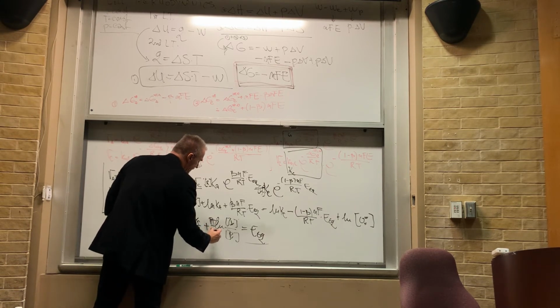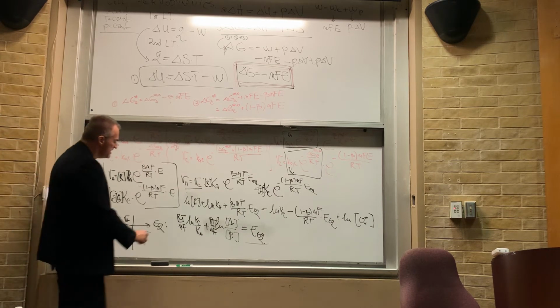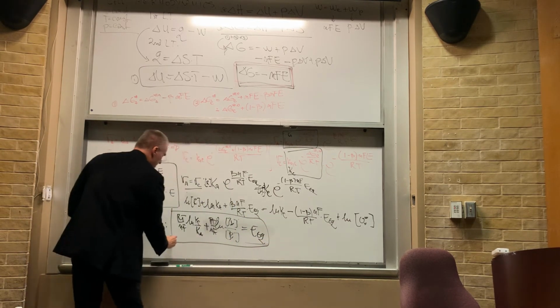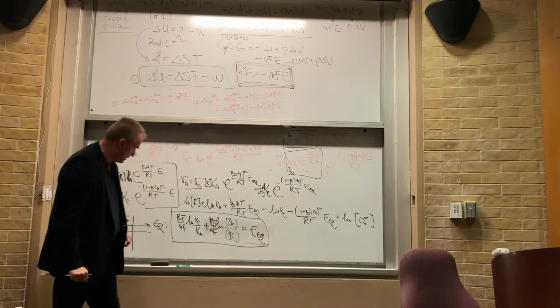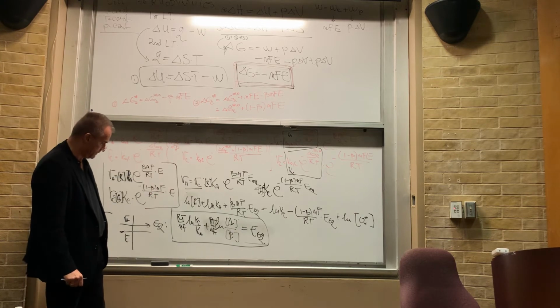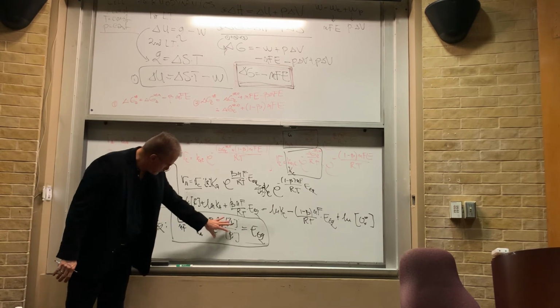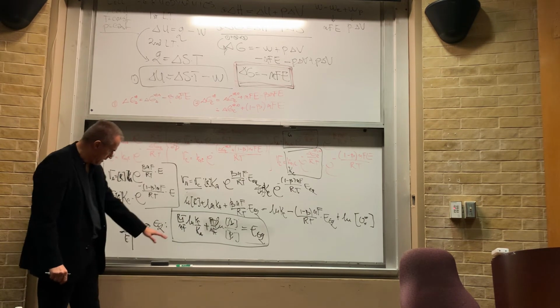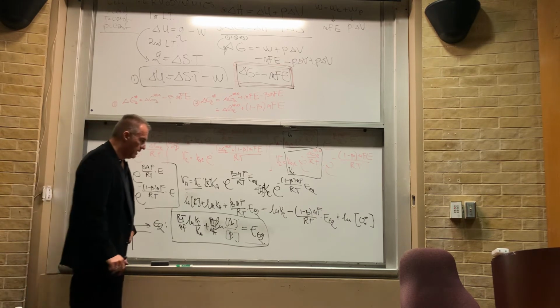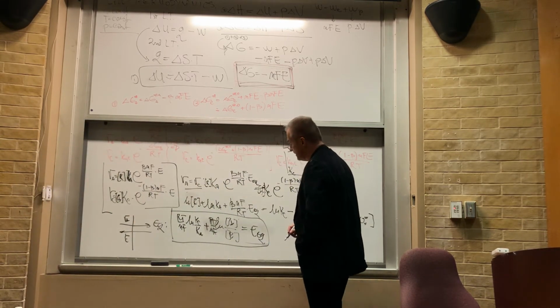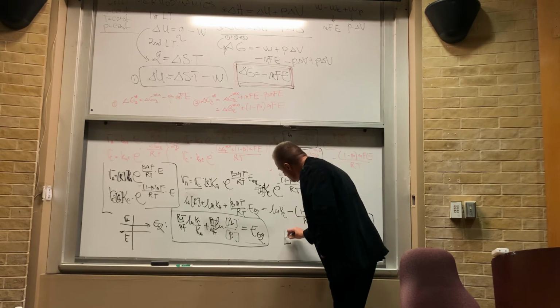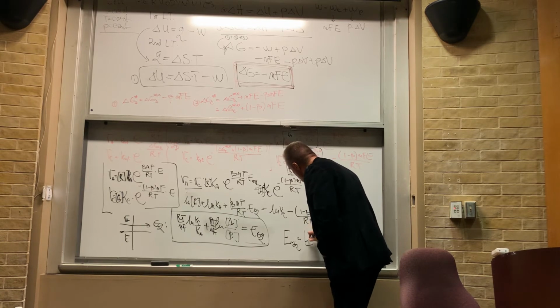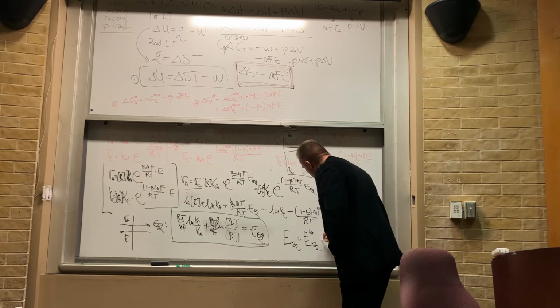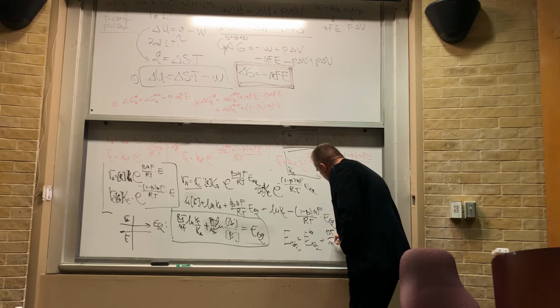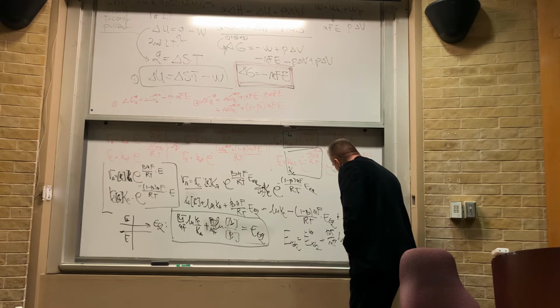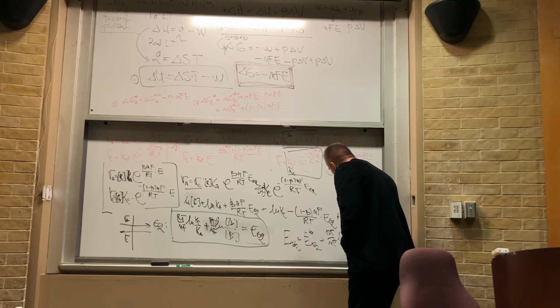All right, this equation here seems to tell us that the equilibrium potential, at which the rates of the anodic and cathodic reaction are equal, has a term which is concentration dependent and a term that is not concentration dependent. Now, the classical definition of the Nernst equation tells you that the equilibrium potential is equal to the equilibrium potential at standard conditions plus RT over nF ln, and then you have oxidized species concentration divided by reduced species concentration. Okay?